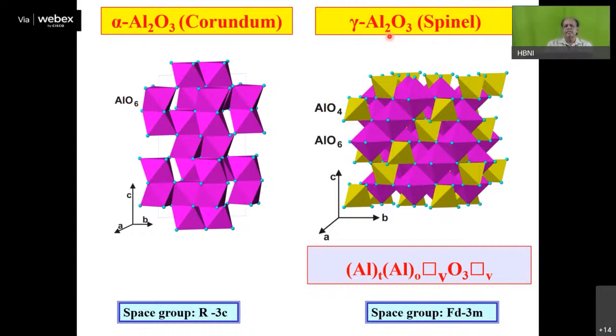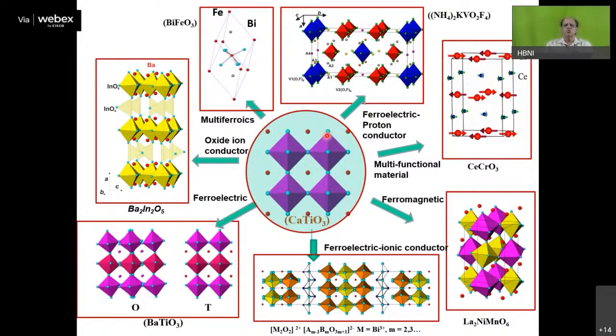Likewise, gamma alumina is used as an active support of catalysts, because here we have got vacancies. We have got one oxygen vacancy and we have got cation vacancy also. So we have one vacancy of cation and one vacancy of anion. Because of presence of these point defects, gamma alumina has got high surface energy, and in turn it is a much better active support for many catalytic materials compared to alpha alumina. So for catalysis, you use gamma alumina, not alpha alumina, and for laser host application, you use alpha alumina, not gamma alumina. This is a typical example of the role of structure in imparting a given functionality.